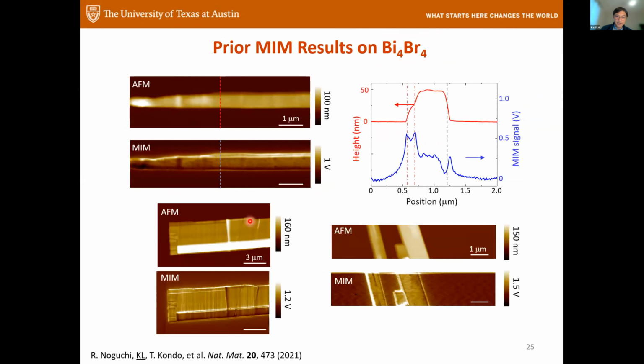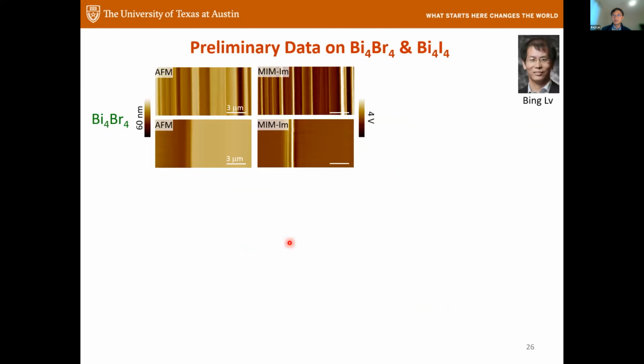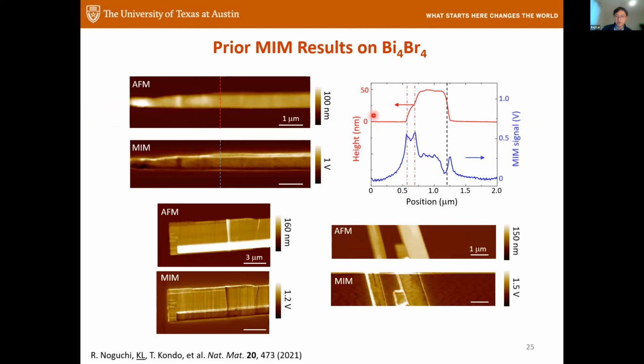So if you pay attention, these ones are like a micron in width. We can get wider, but it's not that large. But from UT Dallas, those samples are huge, like very large dimensions. So here I just show a number of results on the bismuth bromide. Right? So you see the common feature is this is huge. So let me come back here. These are all volts. Volts to us are very large.